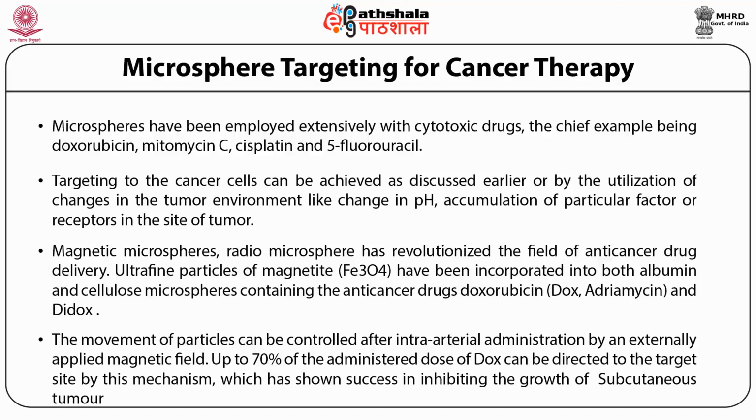A recent patent from Japan described new technology in the form of porous silica microspheres coated with ferromagnetic ferrite. The inventors claim uses of the technology for ultrasonic diagnosis and dermatology, in particular the treatment of solid tumors utilizing heat generated through converged ultrasonic waves. Therapeutic efficacy was demonstrated after direct injection of microspheres into the liver of rats inoculated with tumor cells. Tumors were irradiated with ultrasonic waves of 2 MHz frequency and 10 watts for 3 minutes, and temperature was raised by 5 degrees Celsius, resulting in tumor cell death.